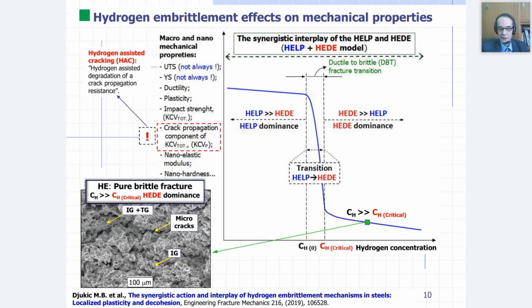And as you can see on the down left microstructure figures, we have a typical pure brittle fracture and a sharp drop of mechanical property characterized by the intergranular and transgranular fracture features and micro cracks when we have an actual hydrogen concentration above the critical. So the affected mechanical properties are tensile stress, yield stress, but not always. So in some cases there is no big change in tensile stress or yield stress, but ductility and plasticity are almost always affected, and what is the most important, the crack propagation component, which means the fracture toughness of material, sharply drops, which finally provokes the fracture of the component due to activation of the decohesion mechanism.